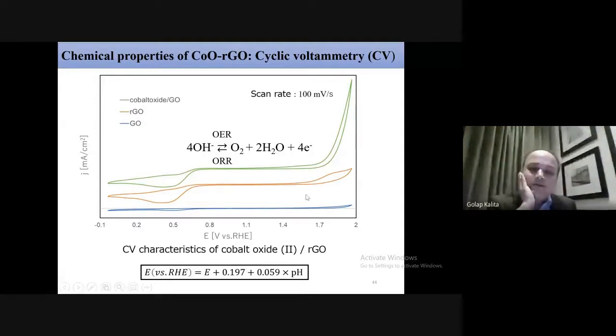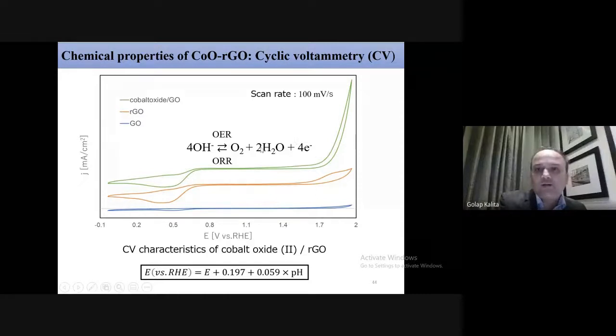This is a CV analysis. When you have CV analysis, you can see a very clear OER. This measurement was done with a silver chloride electrode, and we are converting it to the RHE scale. In the RHE scale, the reaction onset potential is around 1.7. This is for the cobalt oxide GO sample. Then this is the ORR, which means you have both OER and ORR, so you have a bifunctional activity, and it can be used for metal-air batteries.